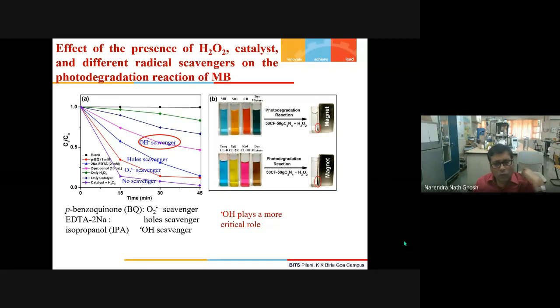Now, our strategy is that whatever the radical or species responsible for the photocatalysis reaction, if we can scavenge them, then obviously it will hugely adversely affect the photocatalysis reaction. Now we have taken parabenzoquinone, which is a known O2 dot scavenger, the disodium salt of EDTA, which is the hole scavenger, and IPA, isopropyl alcohol, which is the OH dot scavenger. With this red graph, you can see we added some parabenzoquinone. We saw that some amount of decomposition has been reduced. I am saying some amount.